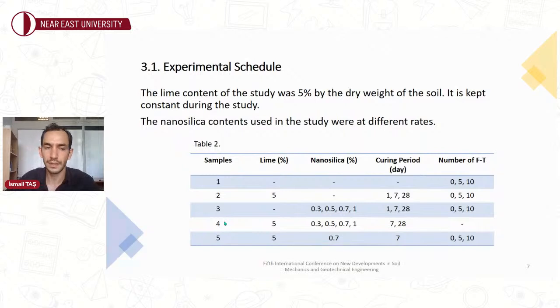The lime content of the study was 5% by the dry weight of the soil, and it was kept constant during the study. The nanosilica contents used in the study were 0.3, 0.5, 0.7, and 1%. Firstly, the dry soil and lime were mixed. Then nanosilica was dissolved in water with a high speed mixer and added to the dry mixture. The water content of the specimens was adjusted to their optimum water contents. You can see the details in the table.